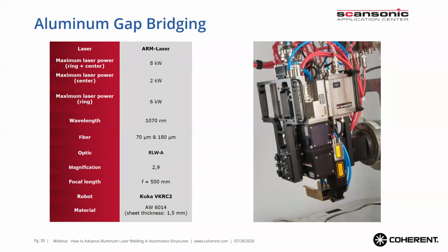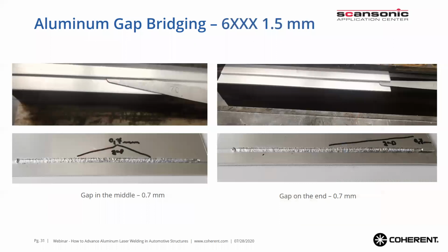So in this case, they used their head and our laser to do a gap bridging study in aluminum. What they found is, as you see on the left side here, they added a 700 micron gap in the center of a part where they were doing a fillet weld. And they also did the same, adding the gap on the right side of the weld. And as you can see, the process head was able to essentially adjust the laser parameters and the optical parameters to bridge that gap successfully.